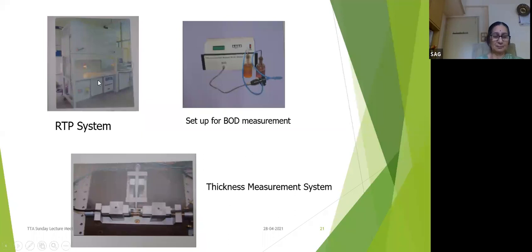We also developed a fabrication system, or sensor treatment system, known as rapid thermal processing. Sometimes in silicon technology, when you are using a few wafers and heating them in a conventional resistive furnace, it requires maybe half an hour or so to get a stable temperature. Sometimes we are not able to spend that much time, and the processing time can be reduced by the rapid thermal processing technique, wherein optical absorption of the silicon is used for heating it, and therefore processing time goes to a few minutes rather than a few tens of minutes.